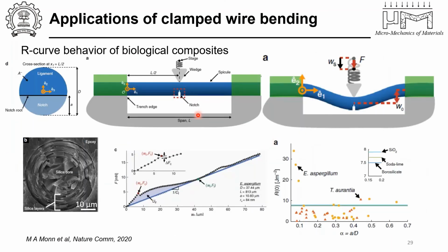Then this was a recent work that we came across, which uses the clamped wire condition in bending, using a biological composite which has a cylindrical structure with a circular cross section. If you can see the dimension, this is just about 20 microns in its cross section. And they could make a notch and determine what is called the R curve behavior of biological composites and explain the mechanisms, again because you can stabilize the crack.